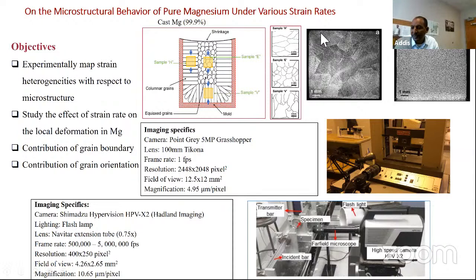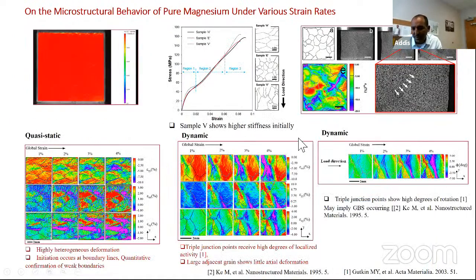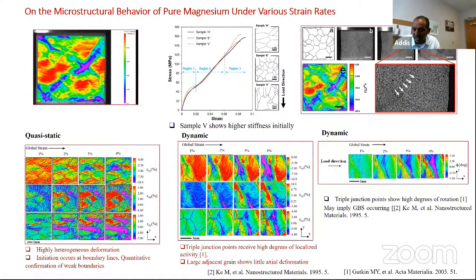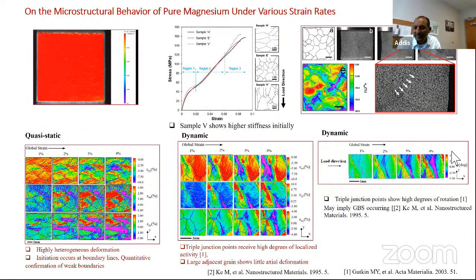This is what the microstructure looks like before speckling. Then you speckle it and do the experiment. When you subject it to the experiment, this is digital image correlation, giving full-field displacement and strain fields. What we found is that the global stress-strain response is pretty much the same, except for small changes at the initial stage. The sample with the grains in the vertical direction is a little bit stiffer compared to the others. Otherwise, the response is somewhat similar.